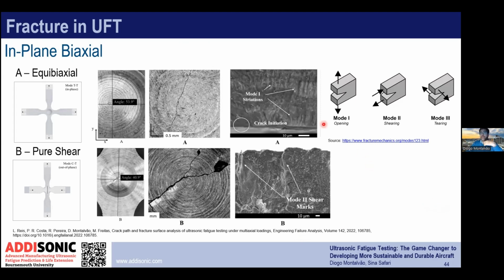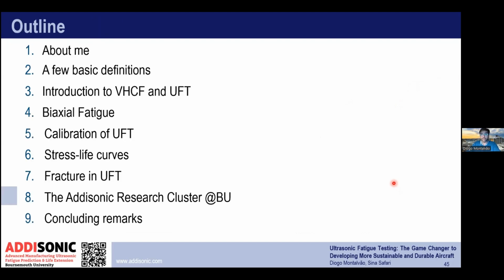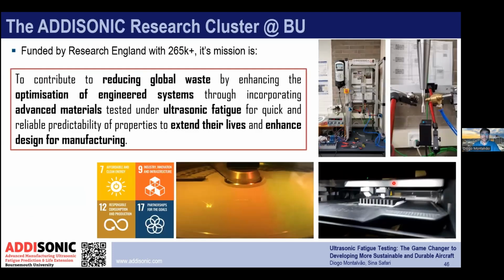In biaxial fatigue, not going into much detail, for those who know about fracture, there are 3 types of modes in fracture mechanics. When we have equibiaxial loading, stretching from 2 orthogonal directions, we have mode 1 striations, meaning we're getting opening as expected. The angle at the center is 53 degrees, not too bad, as we're looking for 45 degrees. In pure shear, we got 40 degrees at the center of the fracture, and we have shear marks, which is mode 2, as expected, and then there is a bifurcation, which has been observed by other researchers before in aluminium.